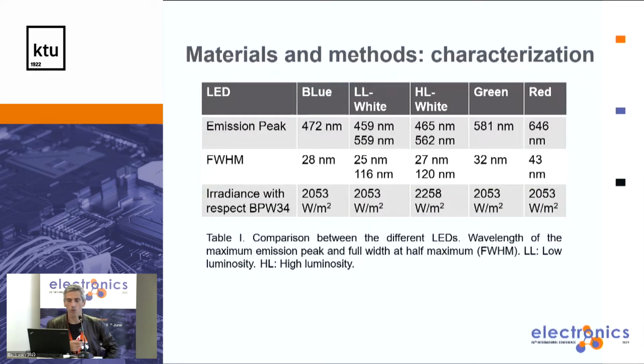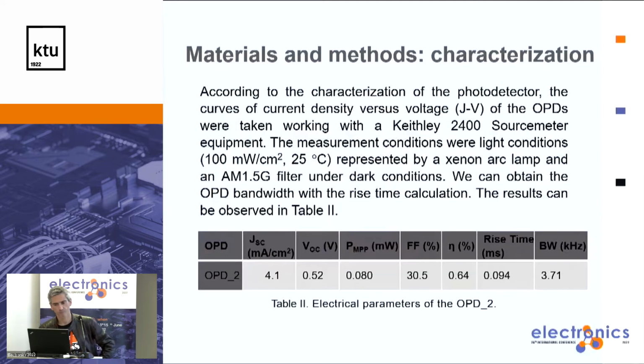In the first table, we can compare these different LEDs, blue, low luminosity, high luminosity, green or red, related to emission peak, full width at half maximum, and irradiance if we compare with a commercial OPD. And we can obtain a characterization related with the curves of current density versus voltage. In that case, the most important values are related with efficiency and the rise time, because if we know the rise time, we can obtain the bandwidth of our OPD.